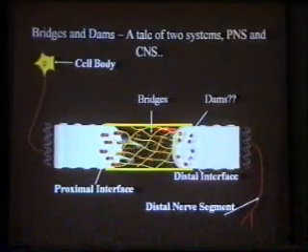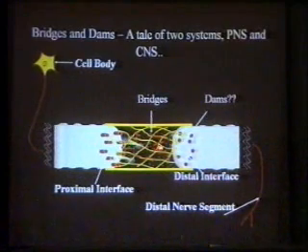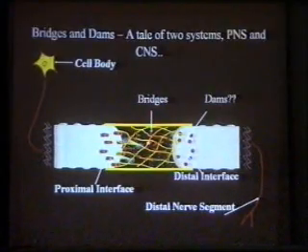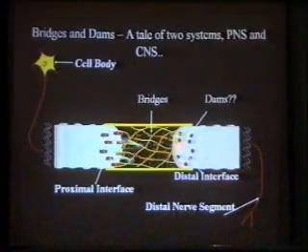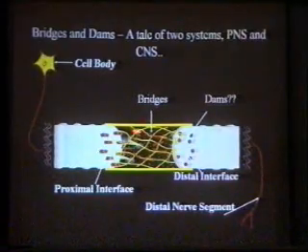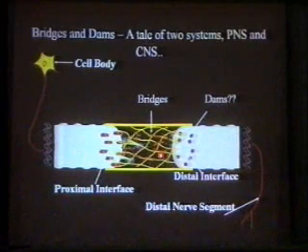You have a proximal nerve end and a distal nerve end. You need to design it such that whatever you put in here supports neurite extension and nerves like to grow in. You can introduce, perhaps, if you use a polymer here, perhaps you can bind things to the backbone to introduce the so-called haptotactic component, where if you know the proteins like laminin, which are responsible for haptotaxis, perhaps you can bind them here. If you know the chemoattractive proteins, perhaps you can embed within this microparticles like Pat Staten was telling us about, or in our case, we do something else. But you have some system to release a trophic factor that attracts the nerve to come in.